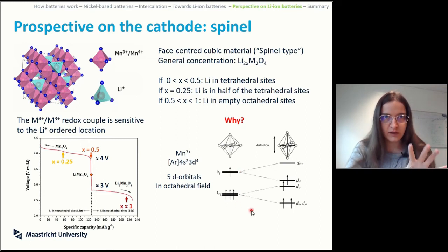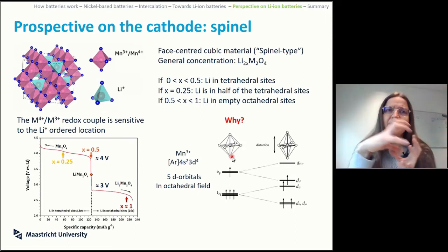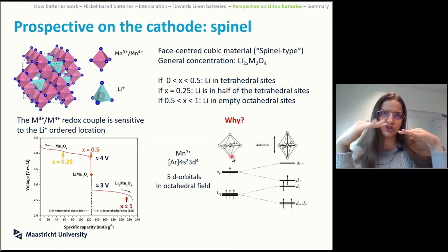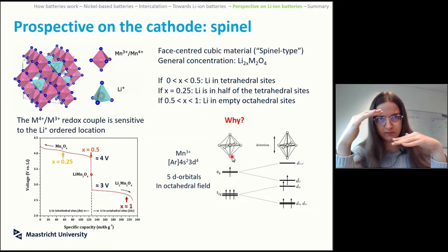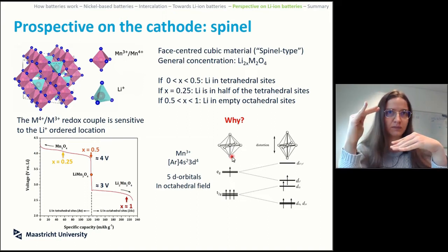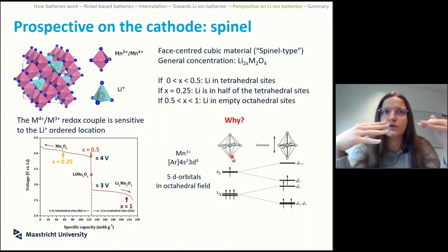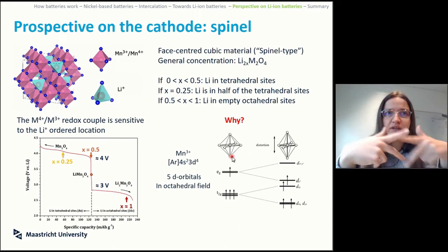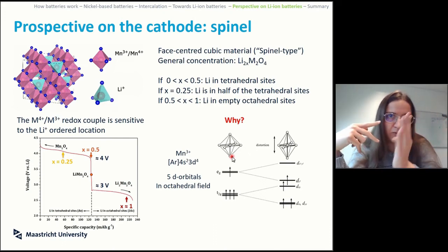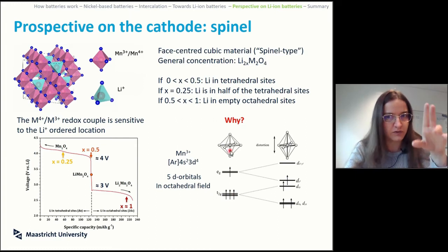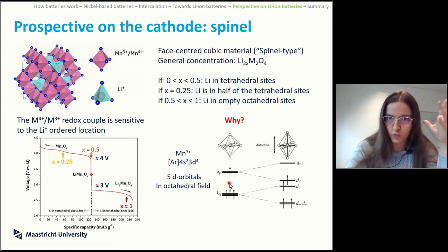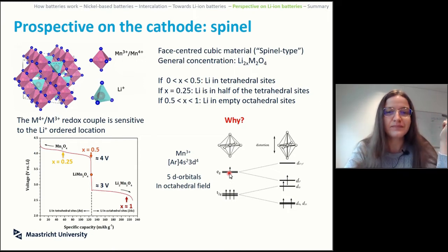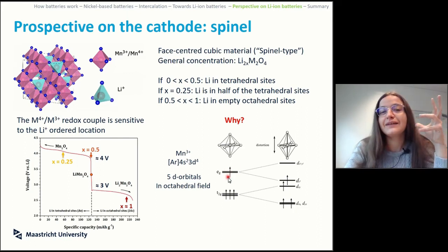So 5 d orbitals, as usual. But we know that in octahedral coordination they kind of sense a slightly different energy. So instead of having 5 degenerate orbitals, you end up with a split of 3 orbitals and 2 orbitals on top. They are relatively close to each other. So when you have your 4 electrons, you still apply Hund's rule and the Pauli principle, 1, 1, 1, 1, and you have this configuration of all of them going through. Now, the issue with this is that it has a series of energy levels that are exactly the same, right?